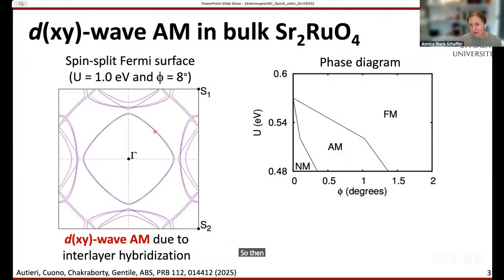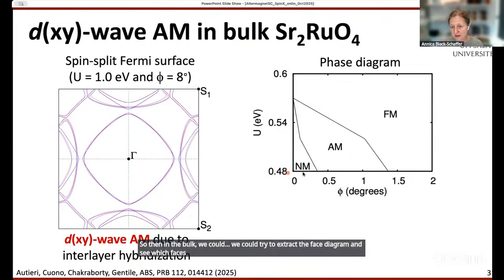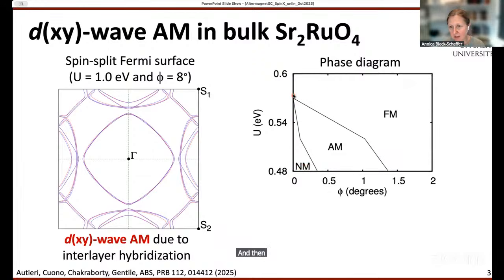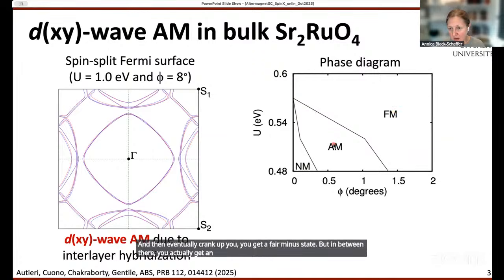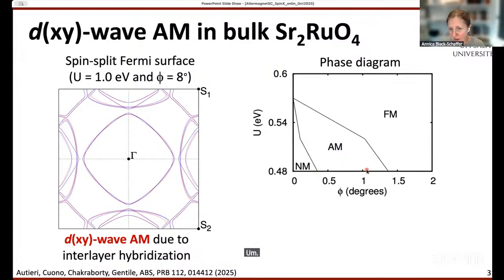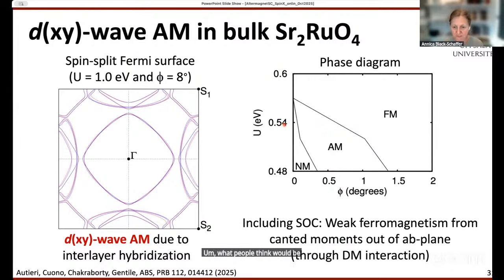So then in the bulk, we could try to extract the phase diagram and see which phases we get. Here are the phases plotted as a function of this distortion angle and the U. And that's the regime where we think the material should be in this DFT plus U calculation. You have a normal state, and then eventually as you crank up U, you get a ferromagnet state. But in between, you actually get an altermagnet state for some reasonable angles and in U, which seems to be what people think would be the relevant U in this material.